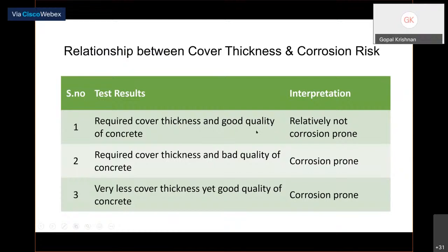Required cover thickness and good quality concrete, relatively not corrosion prone. With the cover thickness and bad quality concrete, yes, definitely the porosity will increase, corrosion prone zone. Less cover, even if you are having good quality, again it will be corrosion. We can correlate the result based on these techniques.